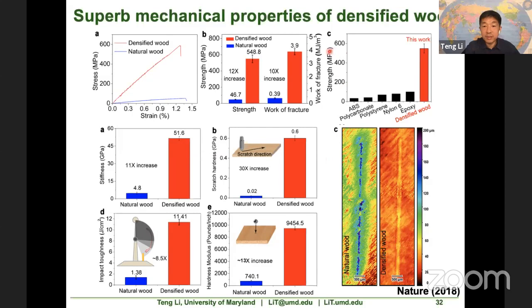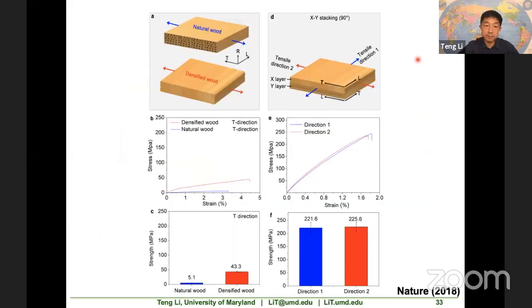Now, if you compare the absolute strength of densified wood with typical plastics, because the density of the densified wood is 1.2, 1.3, it's comparable to typical plastics: ABS, PC, polystyrene, nylon, epoxy. As you can see, the strength is significantly higher and sometimes more than one order of magnitude higher than those materials.